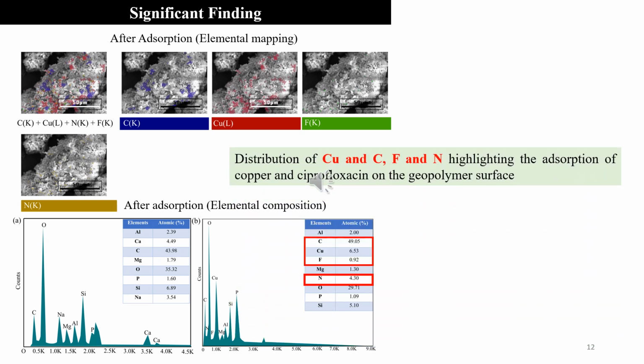After adsorption, elemental mapping and also elemental composition analysis was conducted on the geopolymer surface. The distribution of copper, carbon, fluorine and nitrogen highlights the successful adsorption of copper and ciprofloxacin on the geopolymer surface.